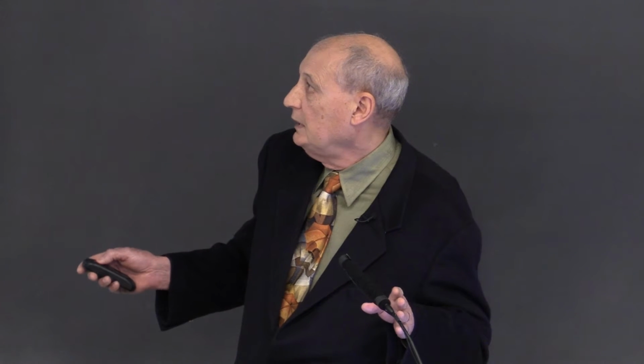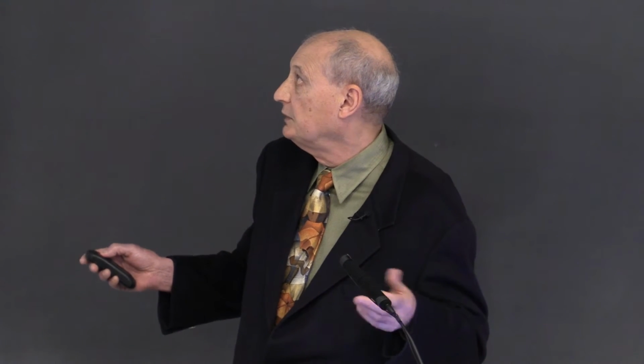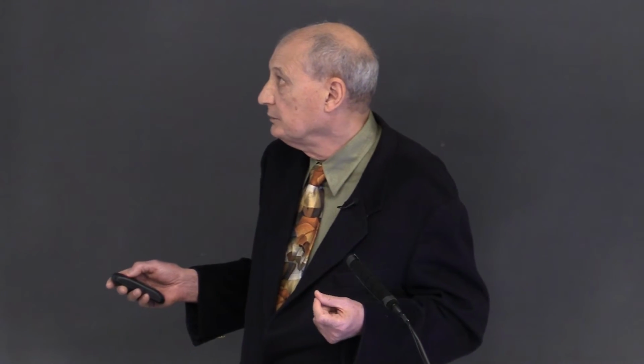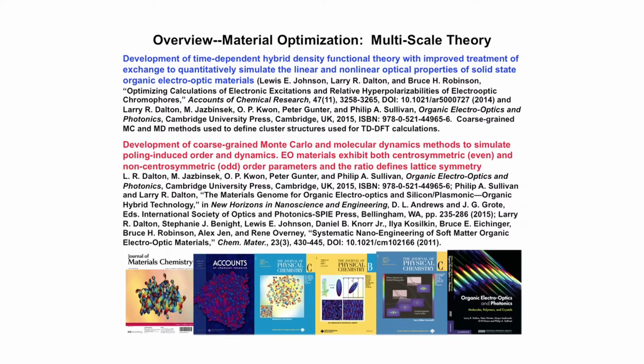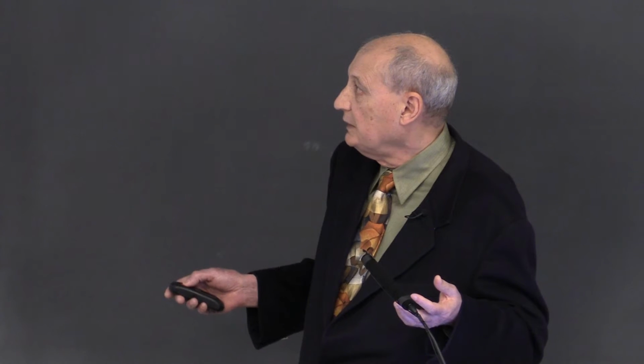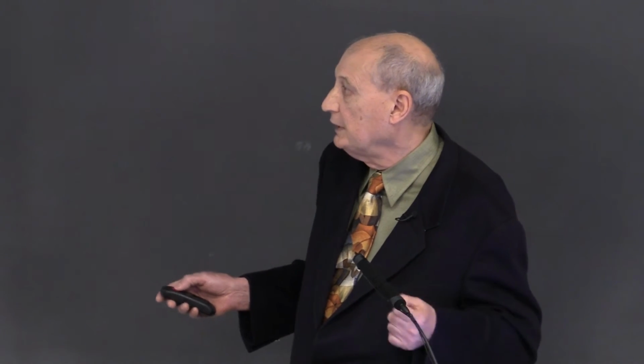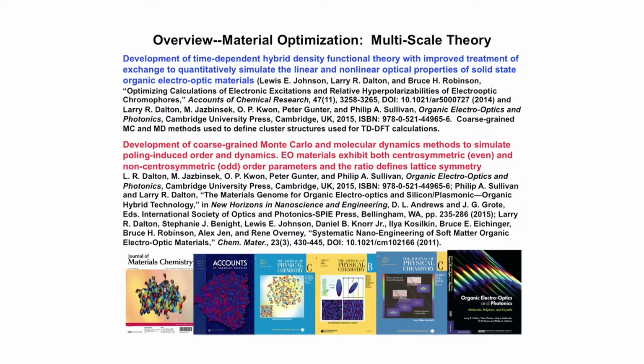And there are two components to this. The first component is using time-dependent hybrid density functional theory for calculating linear and nonlinear optical properties of our materials, and using that theory to guide the next chromophores to be produced. We also need to develop coarse-grained Monte Carlo and molecular dynamic statistical mechanical methods to simulate poling-induced order and dynamics. And we note that electro-optic materials exhibit both centrosymmetric, even, and acentric, odd order parameters, and that the ratio of these define lattice symmetry. So this is a great system that experimental data allows us to do a really good test on theory. And these are some of the publications that have described various theoretical methods.